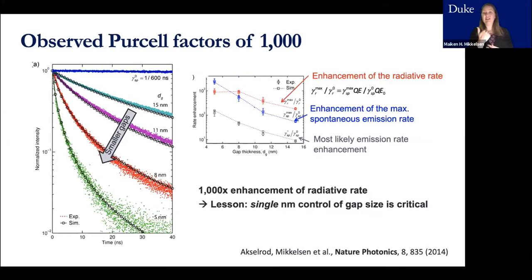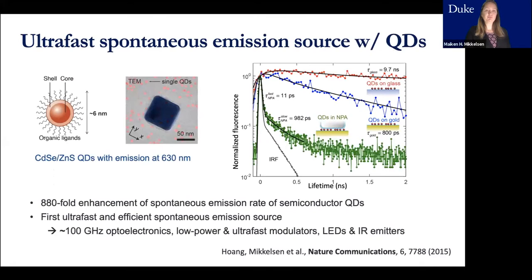One is that we can indeed get reproducible, very large enhancement in the spontaneous emission rate. But in order to do that, we really need to have control on the single nanometer scale, which was not, I think, fully appreciated in the community beforehand. And we have to then think about alternative fabrication techniques to be able to get this type of control.